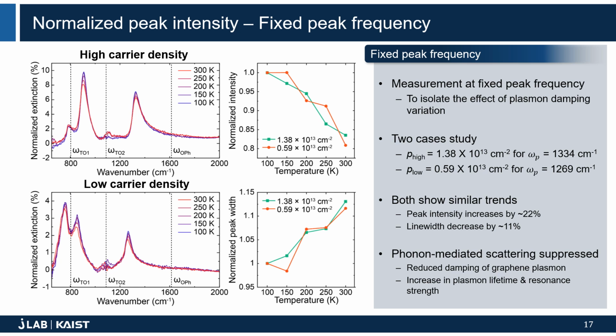Interestingly, the temperature dependencies of both normalized intensity and line width of the GP peak show a similar trend independent of doping level. We attribute this remnant increase in peak intensity and decrease in peak line width to the reduced damping of graphene plasmons. As temperature drops, the phonon-mediated carrier scattering mechanisms are suppressed. Thus, the plasmon lifetime is expected to be prolonged. It leads to a stronger resonance and increased quality factors.